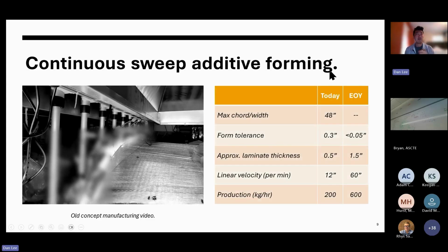The reason I paused it here is that on the left side, you can see it's very loose fabric. We use a 1200 GSM stitched Saertex product. We can use kind of any fiber freeform, but in this case, we used stitched mats of unidirectional fibers, and this had 13 layers of glass in it. But you can see over here it's loose. This is the broad set of engineering heuristics that we think about. This is where we are today. I would say this was last year, and this is where we hope to be by the end of the year.